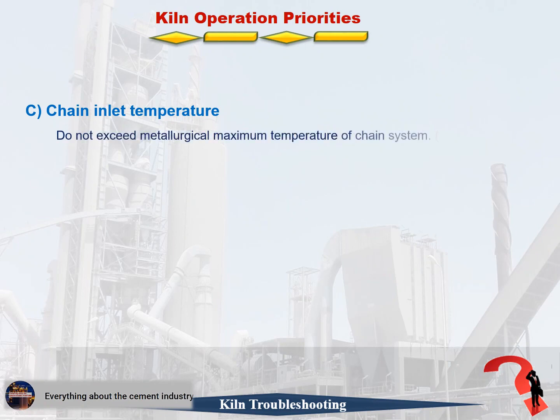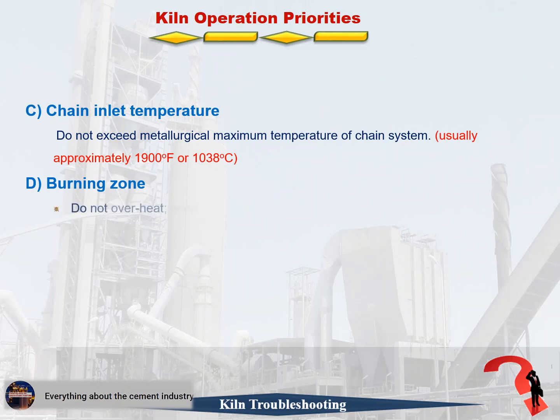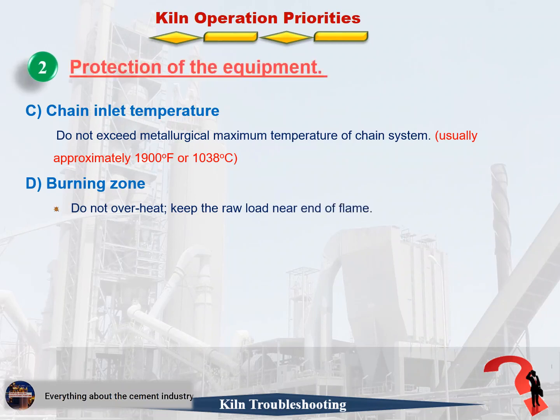C. Chain inlet temperature. Do not exceed the metallurgical maximum temperature of the chain system, usually approximately 1038 degrees. D. Burning zone. 1. Do not overheat, keep the raw load near the end of the flame. 2. Set a maximum amps level on the kiln motor.